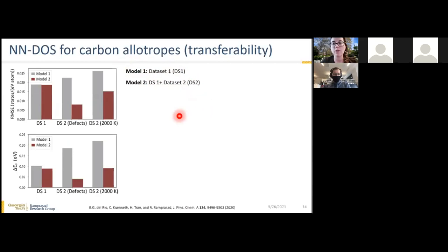So if we look at the root mean square error and the mean absolute error in the Fermi level calculation with model 1, shown here by the gray bars, you can see that there is a worse performance on dataset 2, both for the defects and the highly disordered structures. But given the considerable difference between the atomic environments and the different types of carbon hybridization between dataset 1 and dataset 2, the results are still surprisingly good. I mean, they're worse, but not that much.